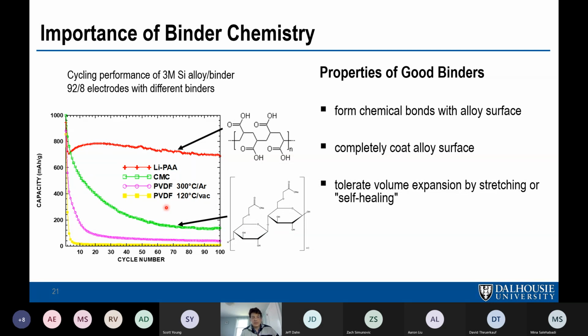I should say, though, that the interesting thing is if you, for instance, make an alloy coating with phenolic resin as the binder, and then you heat the coating to 600 degrees C and carbonize it, the cycling will be very good. And so you can just carbon coat everything and get good cycling as well. So, you know, the role of having an actual polymer is questionable.